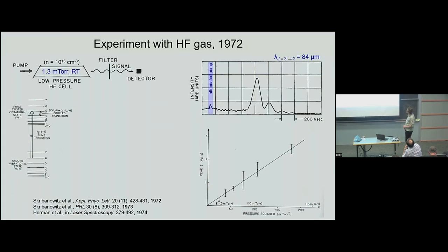What they observed essentially was that in the time signal of this peculiar emission, after the pump there was a delay of some microseconds, which then ended with a burst of radiation coming out in an oscillating manner. Moreover, the peak intensity of the signal was proportional to the square of the number of molecules.